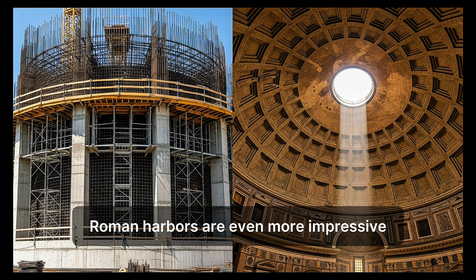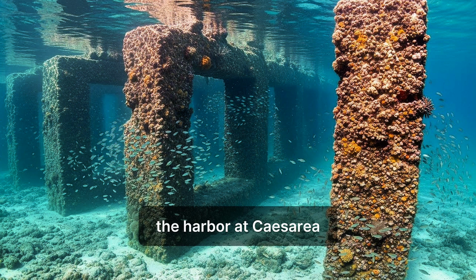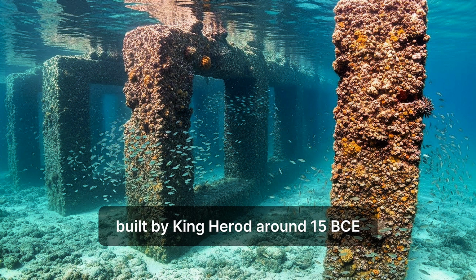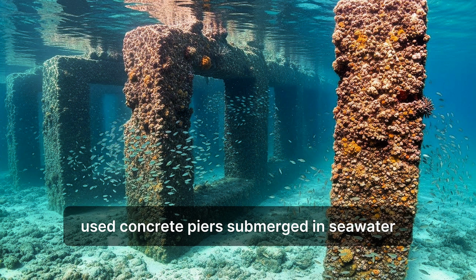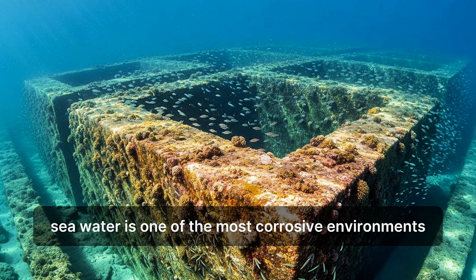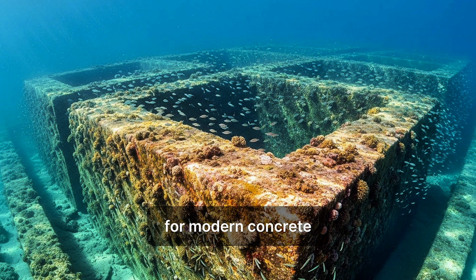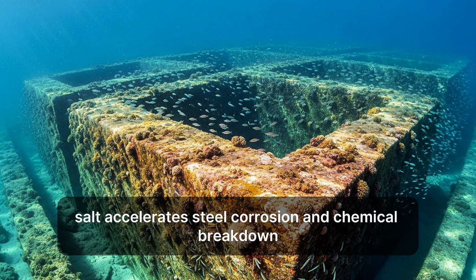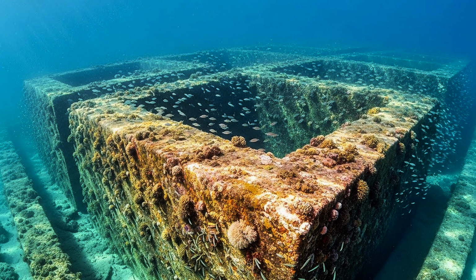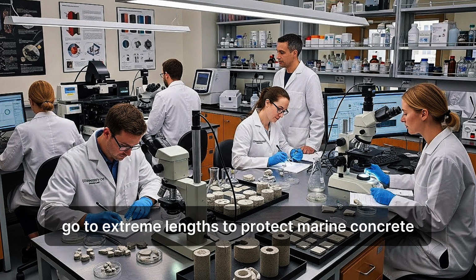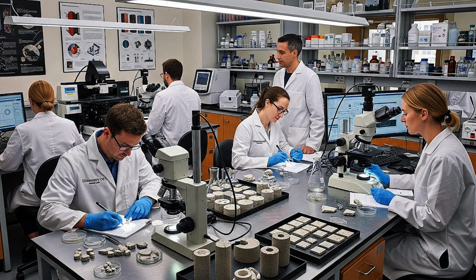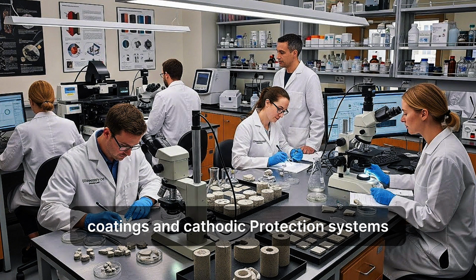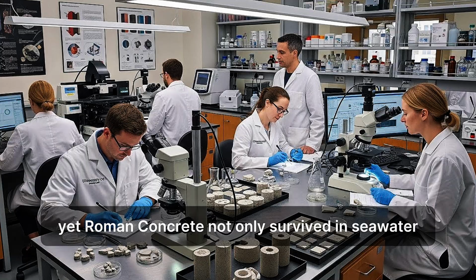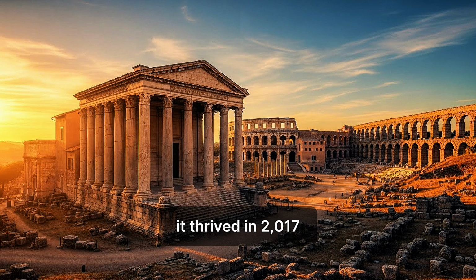Roman harbors are even more impressive. The harbor at Caesarea, built by King Herod around 15 BC, used concrete piers submerged in seawater. Seawater is one of the most corrosive environments for modern concrete. Salt accelerates steel corrosion and chemical breakdown. Engineers today go to extreme lengths to protect marine concrete, using special cements, coatings, and cathodic protection systems. Yet Roman concrete not only survived in seawater, it thrived.